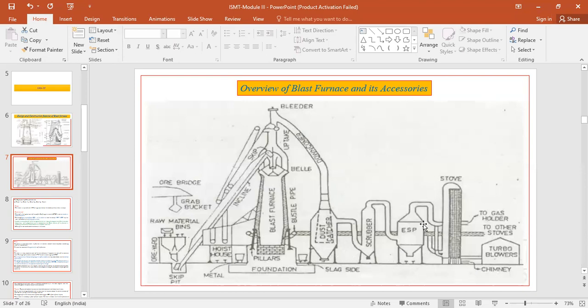So in this picture, you can see three different gas cleaning systems. One is the dust catcher, then followed by the scrubber, then you have the electrostatic precipitator. So these are the three gas cleaning systems, where whatever dust is combined with the off gases will be segregated. And the off gas, which has a very high calorific value, will be sent into the stove,